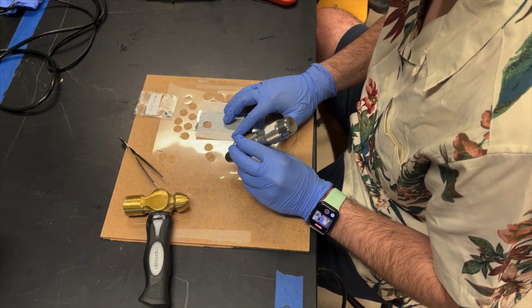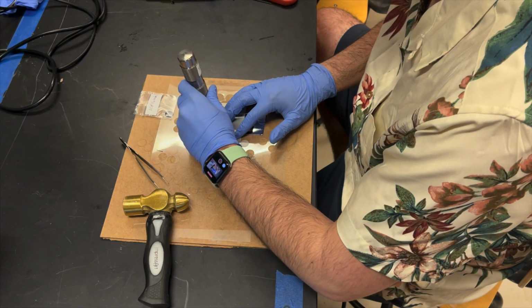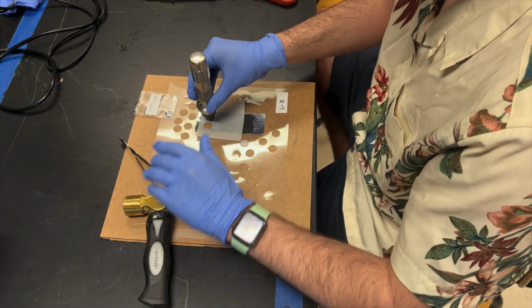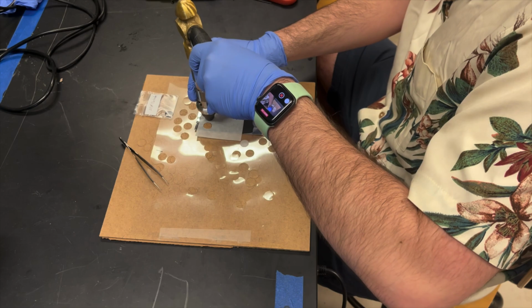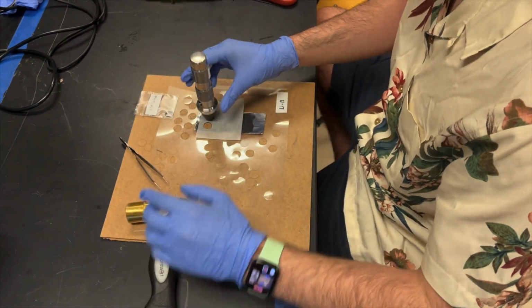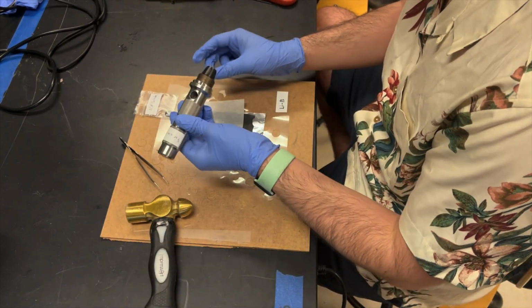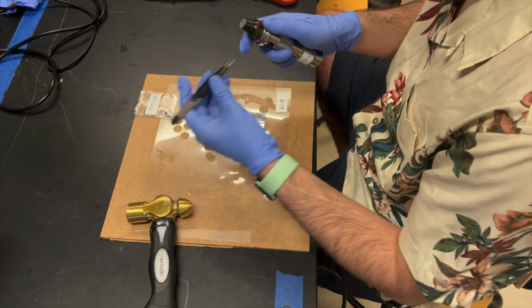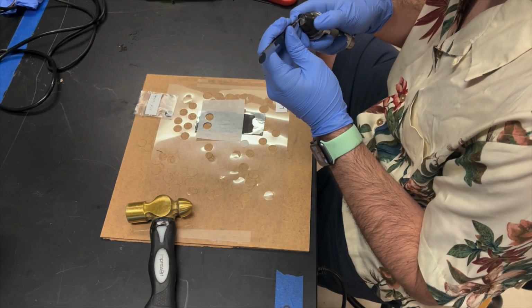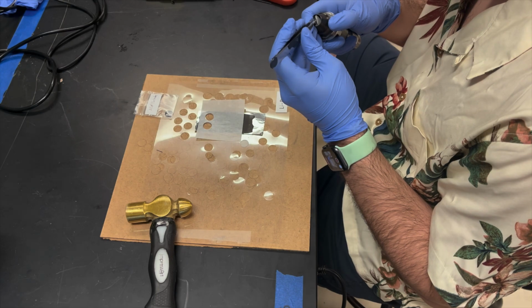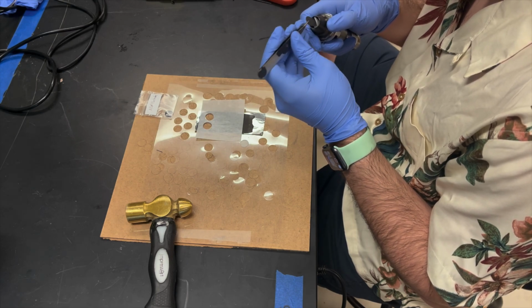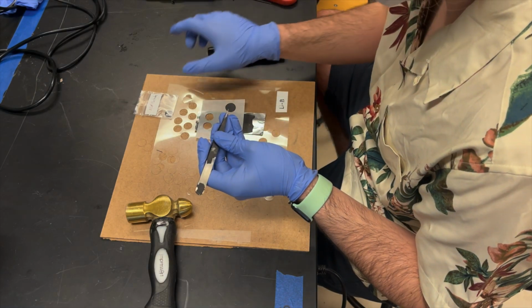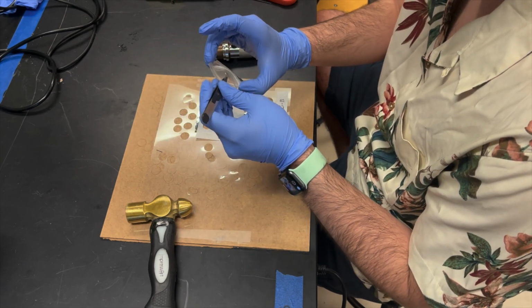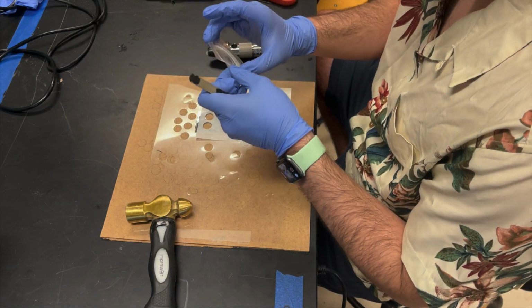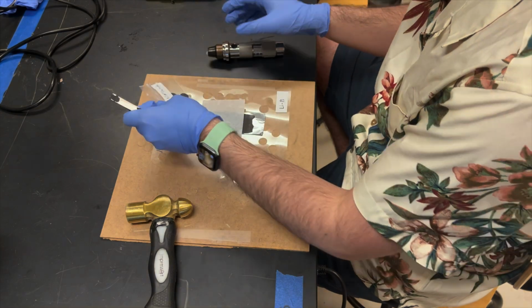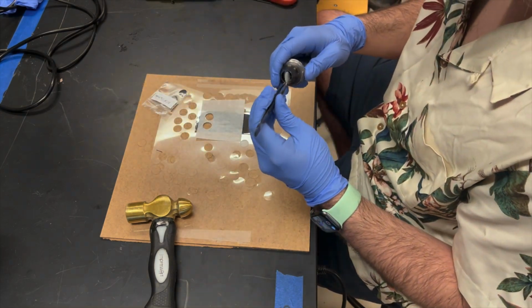Up to this point, I've shown the preparation of the cathode. Making the anode follows the same procedure, but uses graphite rather than the NCM powder. If we wanted to make a supercapacitor, we would use activated carbon for supercapacitors as the active material in both the cathode and the anode. From this, we see that the properties and nature of the devices we make is heavily influenced by the type of active material used, as well as the ratio of materials in the electrodes.